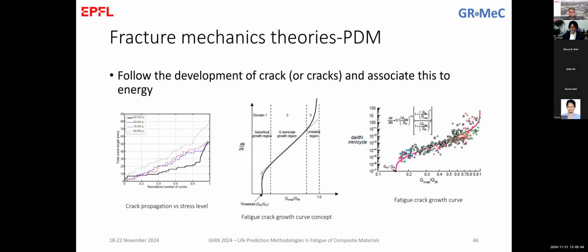And that's why in some cases we prefer to have damage. So there we talk about damage tolerant fatigue designs. We can accept having damage in the material with the condition that we can control or monitor the damage. So if we know that there is damage in the material and there is a crack that propagates at 10 to the -5, it means it needs 100,000 cycles to propagate one millimeter. And we assume that this is safe for our case. And during the next operation, before the next inspection of the structure, we'll do many fewer cycles than this. Then we can assume that for our structure, it is acceptable to live with this small damage there.